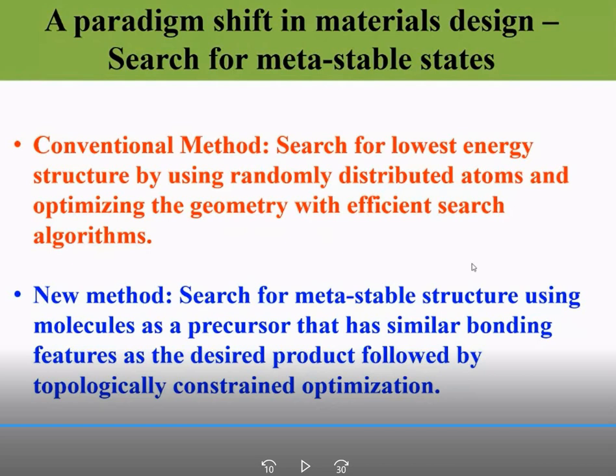The molecule that we chose is called 3,3-dimethyl-1-butene. It has 6 atoms of carbon and 12 atoms of hydrogen. And you just take out all these hydrogen atoms, and that you can easily do by heating this molecule to something like 1200 degrees Celsius.